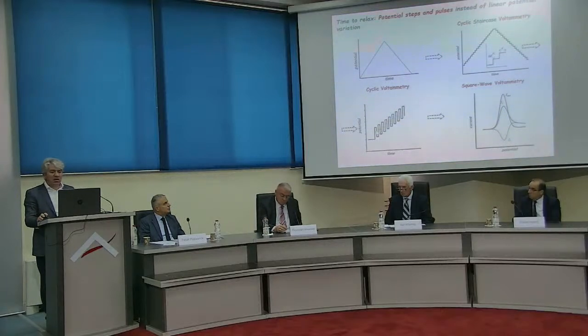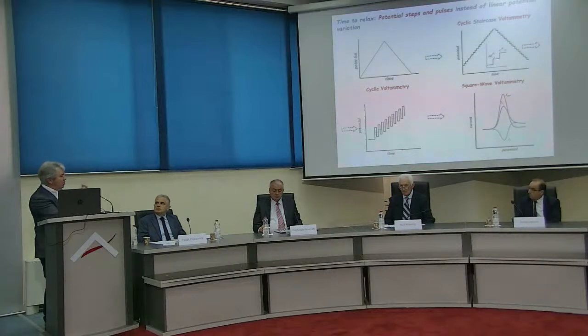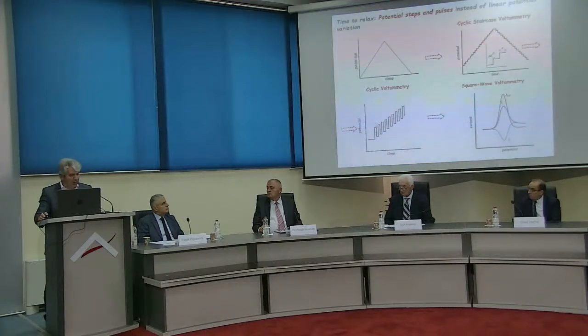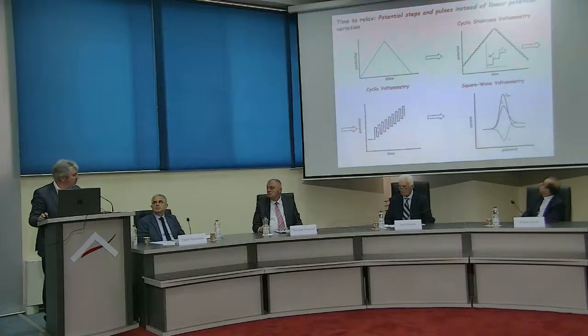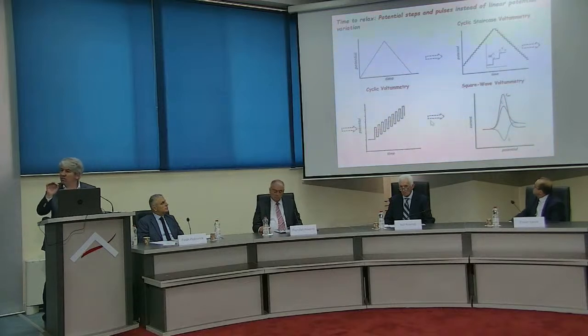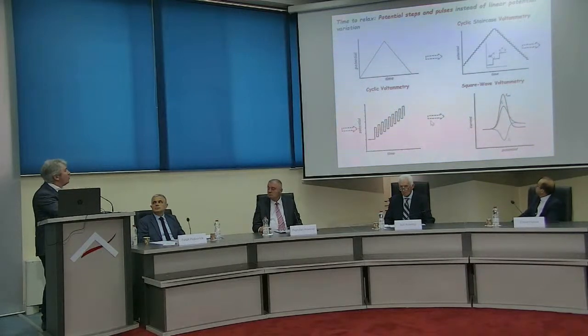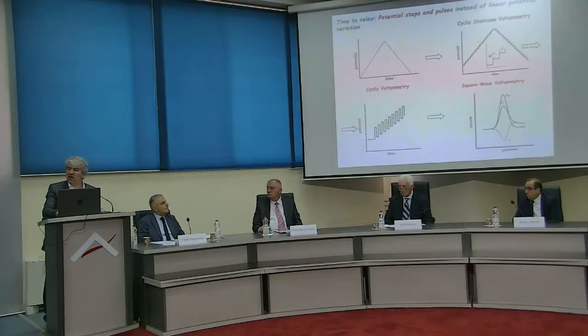Sometimes that experiment could be done even with pulses, which can go up and down like in cyclic voltammetry. I drive the reaction in the oxidation, but also in the reduction direction. And then I can come to a very sophisticated, powerful technique. Pulses, but I measure the current at the end. I see oxidation, I see reduction, and the current is relatively, and sometimes very, clean of the charging current, only the Faradaic component. So that is called square wave voltammetry, a very powerful tool for studying electrode processes generally.